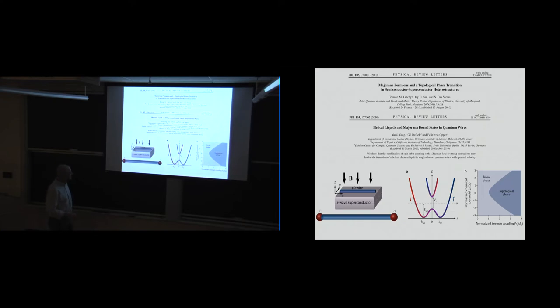And the important thing about this is, as opposed to simply spin lifting the two Kramers pair inside with a Zeeman field, if it has this shape, there's still enough S-wave character remaining that it can be proximitized by an S-wave superconductor. That is, if you just Zeeman split the thing so that this was spin up and this was spin down, that would be fine. You would have a spinless band, but that spinless band wouldn't be able to be proximitized by an S-wave superconductor. But because this thing is spin down when it's moving to the left and spin up when it's moving to the right, it proximitizes with an S-wave superconductor and produces an effective spinless band. This spinless band is the essential ingredient for this Majorana zero mode.